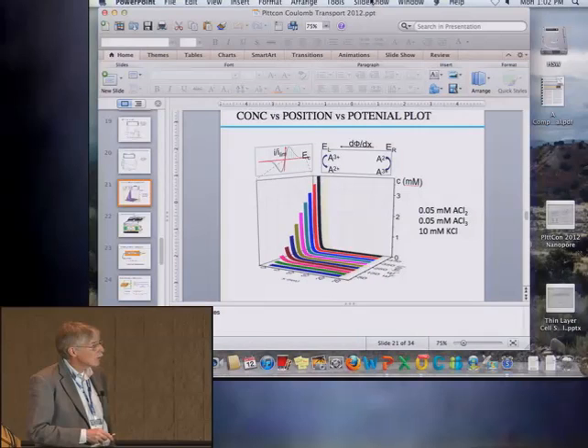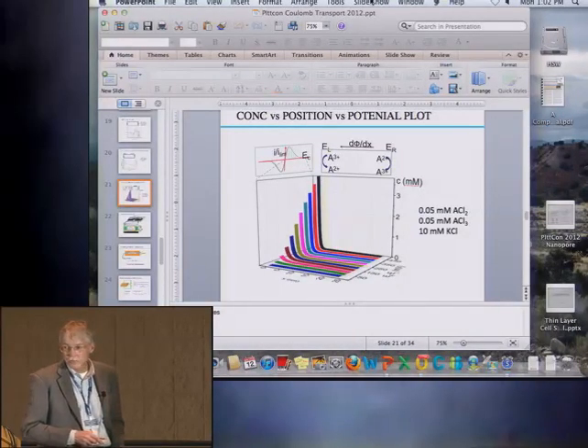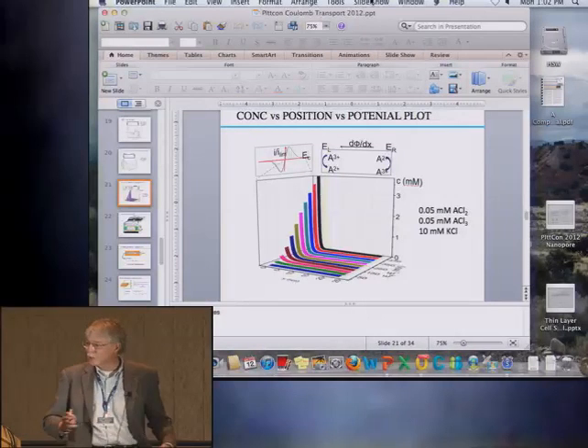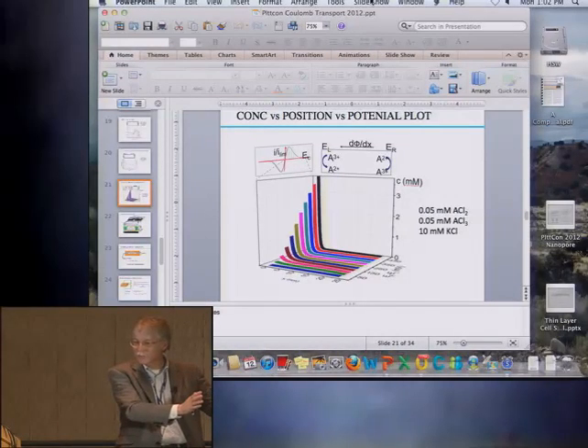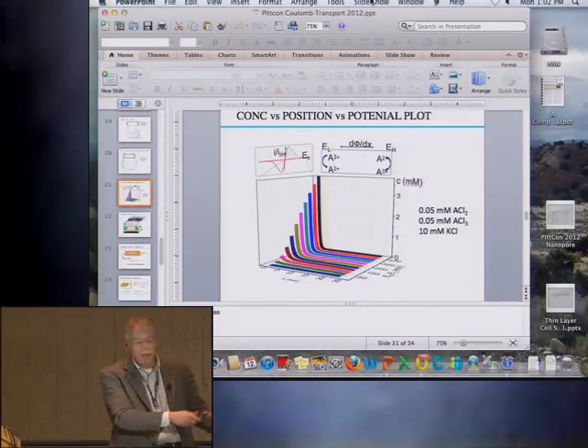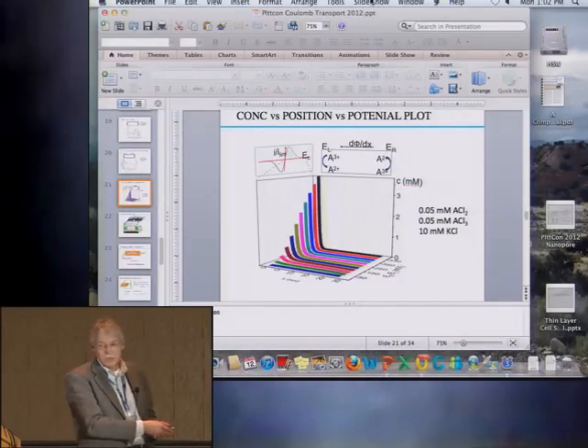If you apply positive potential to this electrode, what you end up doing is sucking all the redox ions out of the cell, putting them on one side next to that electrode, and there's none at the right-hand side necessary to balance the current. And therefore, the cell current in a two-electrode system, without any external ions coming in to balance or shield the electrodes, goes to zero. That's a simulation now.